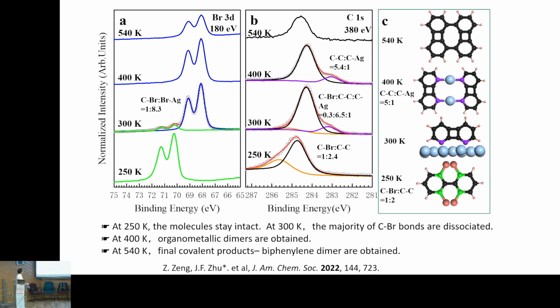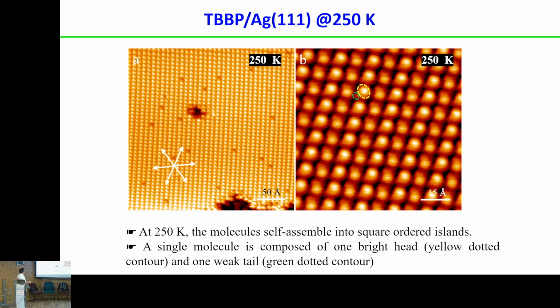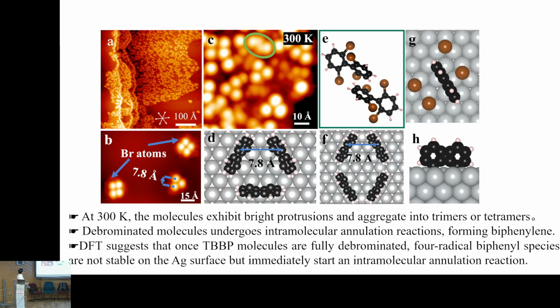So this is the structure model, which is based on the STM measurements. I will show you that at low temperature, when the molecule stays intact, these molecules can self-assemble into an ordered structure, which is nothing special. Then if you go to 300 Kelvin, you see in STM and XPS that the majority of the molecules are debrominated on the surface, and you see trimers, tetramers, and also sometimes dimers on the surface.